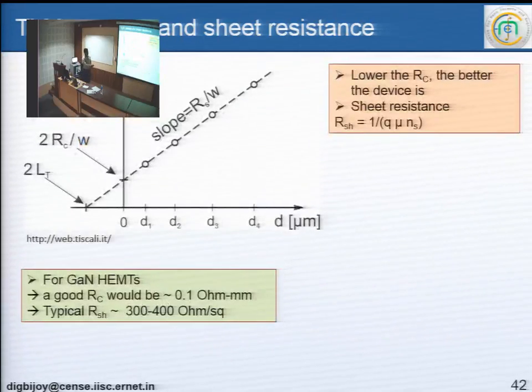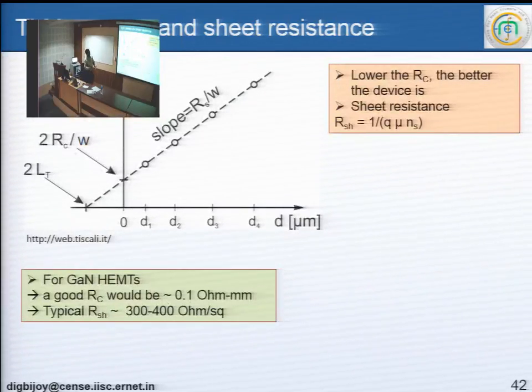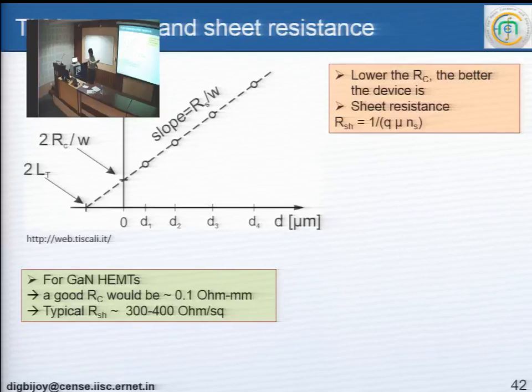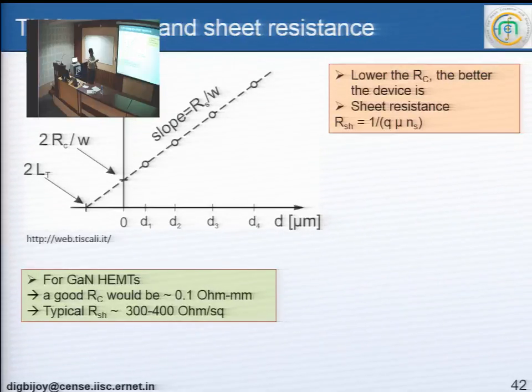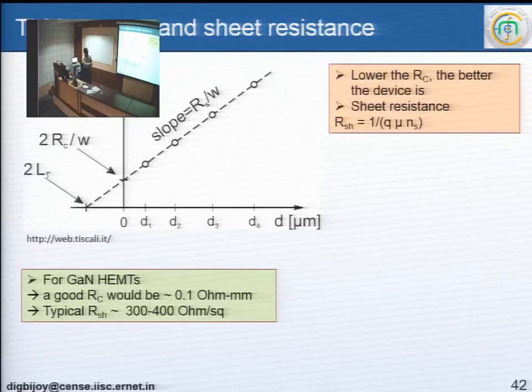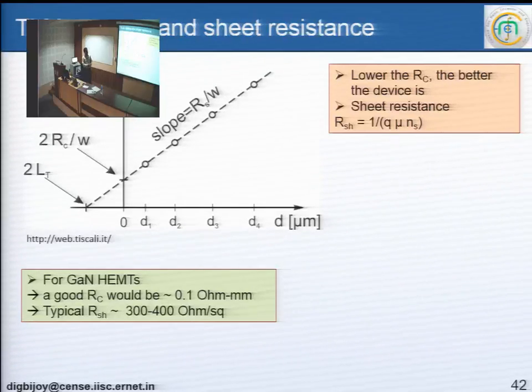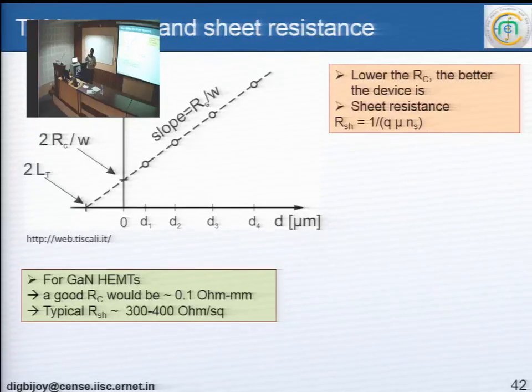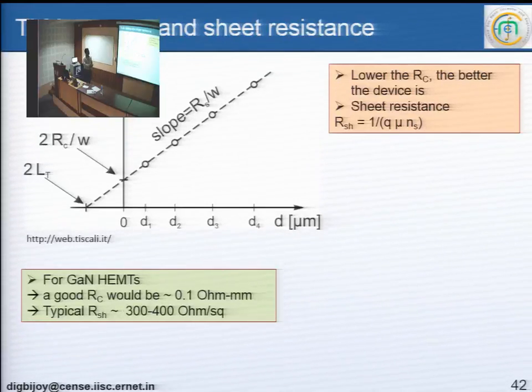So this is the distance across the pads, and this is the resistance. So further the distance, more is the resistance, right? When you plot them, they will fall in a straight line. If you draw a straight line, then the slope gives you what is called sheet resistance. Sheet resistance is the resistance of the channel, and the intercept over here gives you the contact resistance. Like the contact resistance is the resistance that the metal is making with the semiconductor, right? So this is contact resistance, and the slope gives you sheet resistance.